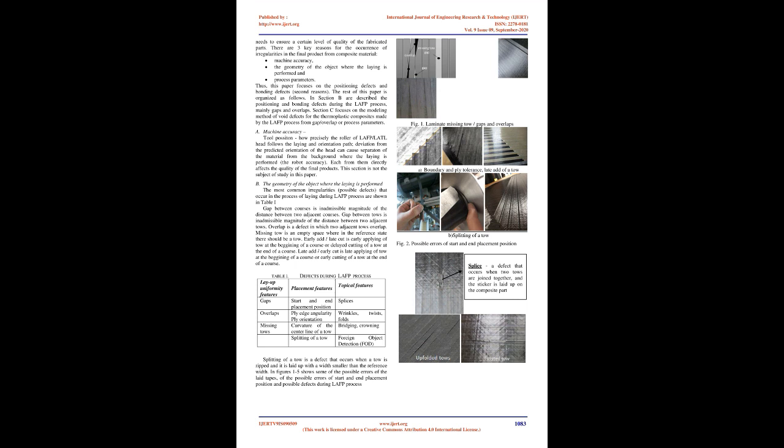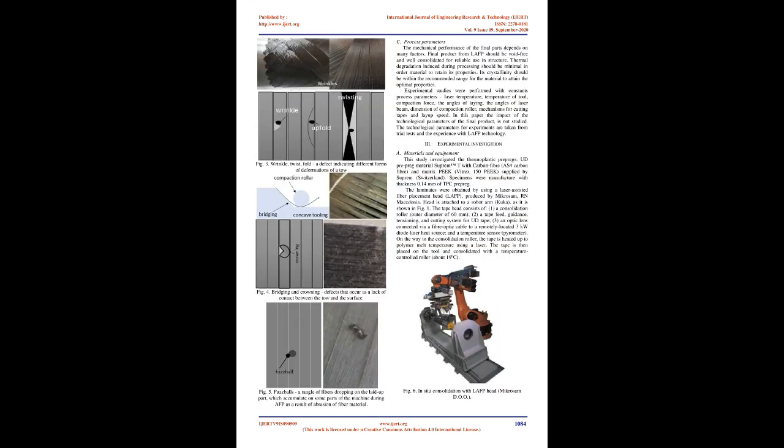In general, slower cooling rates increase crystallinity, which results in higher mechanical properties and chemical resistance in the finished laminate. Chen and Cheng studied the crystallization kinetics of CF-PEEK composites at 61% fiber volume content for both isothermal and non-isothermal crystallization approaches. They showed that a higher cooling rate causes the crystallization to start at a lower temperature and is obtained over a wider temperature range.